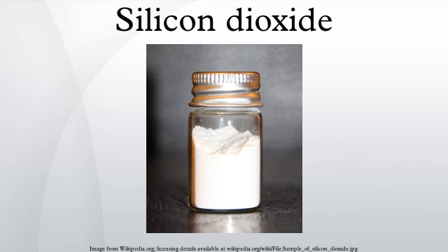Faujasite silica is another form of crystalline silica. It is obtained by dealumination of a low-sodium, ultra-stable Y-zeolite with a combined acid and thermal treatment. The resulting product contains over 99% silica, has high crystallinity and high surface area. Faujasite silica has very high thermal and acid stability. For example, it maintains a high degree of long-range molecular order even after boiling in concentrated hydrochloric acid.